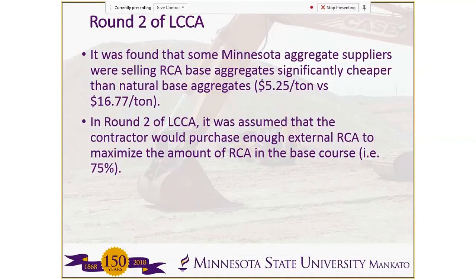We searched and we found that some aggregate suppliers had maybe excess stockpiles of recycled concrete aggregate. They were actually selling this as a base aggregate at a significantly cheaper price, $5.25 per ton versus $16.77 for the natural aggregates. So when we found that, we did a second round of economic analysis where we assumed that, as we said, when you crush up the pavement, the contractor would put that in the concrete pavement. Anything left over, he would put in the base. But now the contractor could purchase some extra RCA from offsite to maximize the amount of RCA in the base course as well.